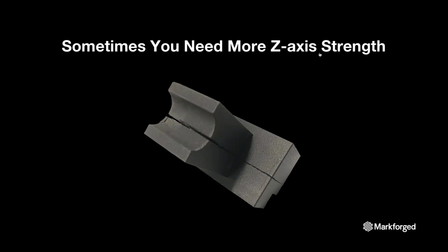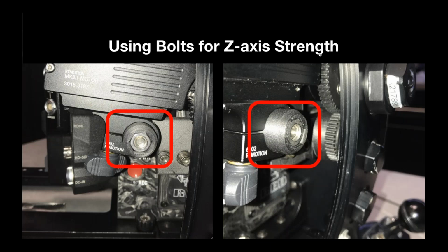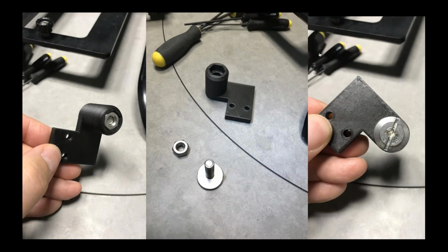And sometimes you need more strength in the Z-axis. If you're familiar with 3D printing, you'll know that inner layer strength, so printing in the Z, when you go up a part, that strength in tension is a lot weaker than your XY when you're printing parallel to the print bed. So how we counter that is using bolts for Z-axis strength, right? For example, this part that was printed in the center picture in that orientation, that column that's rising up is going to be a lot weaker if you pull it in tension. So what do we do? We add a little pre-compression with this bolt and a nut.